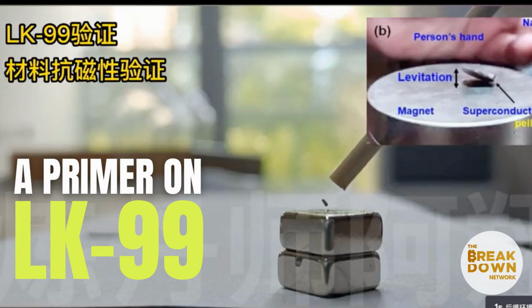The version developed here, which has been termed LK-99, was made by reacting a lead sulfate with a copper phosphorus compound. The reaction requires high temperatures for over a day under a vacuum. This strips the phosphorus from the copper, oxidizes it, and allows it to displace the sulfur from its compound with the lead. Critically, though, some fraction of the lead itself ends up replaced by copper in the resulting compound.